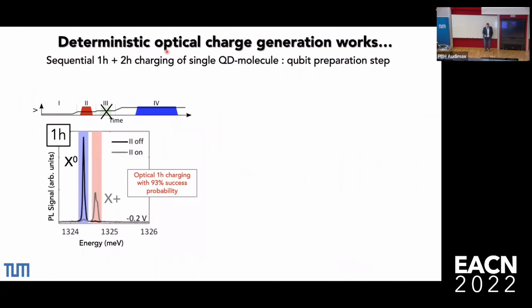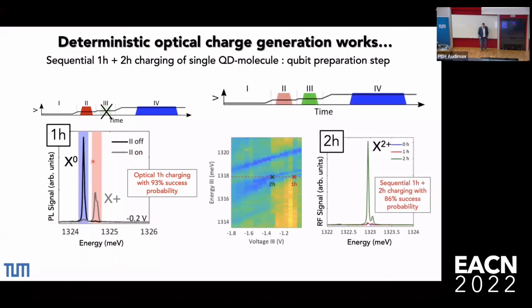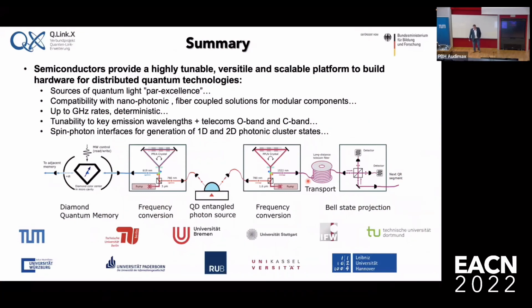Finally, that's the spectroscopy. I claimed that we would like to deterministically place first 1 and then 2 charges in a single molecule. And actually, we've just managed to do this a few months ago. So this is an experiment where we apply 1 laser pulse to place 1 hole in the quantum dot molecule. If you place the hole in, the neutral exciton disappears and the positively charged exciton appears. If you place 2 holes in there, then you see appearing the double charged exciton, exactly like we wanted to have it. So I think we're on a good way, and I hope that at future Q.Link.X meetings and maybe at this meeting, we can present that we've actually built a device we can do some quantum communication with.